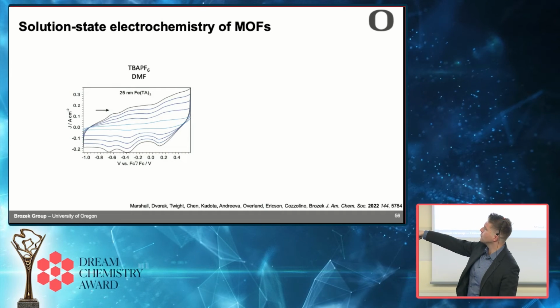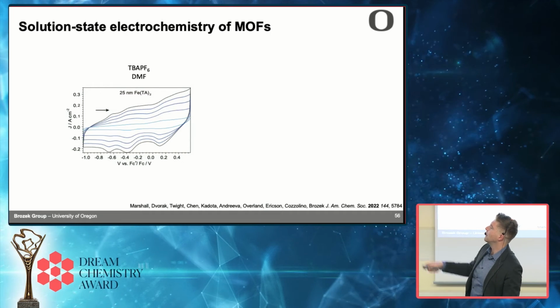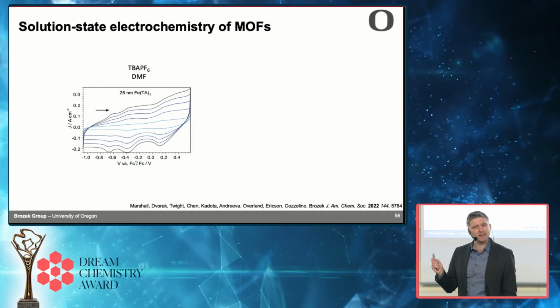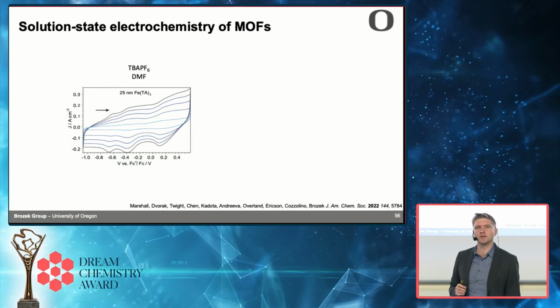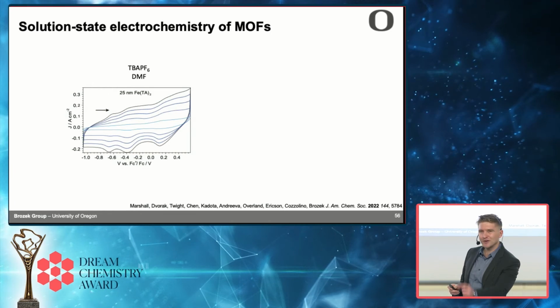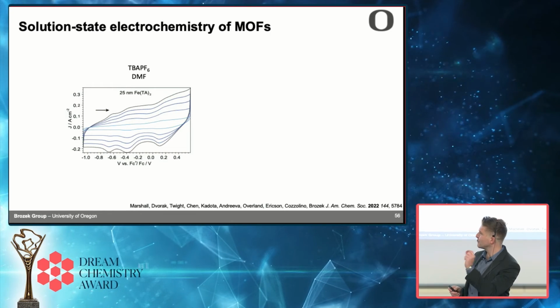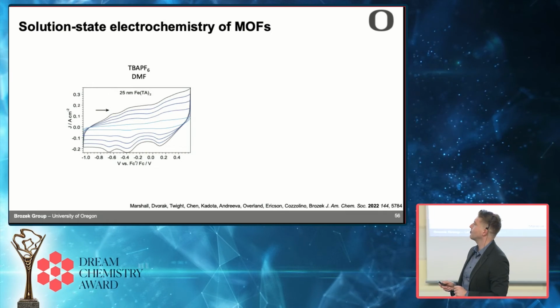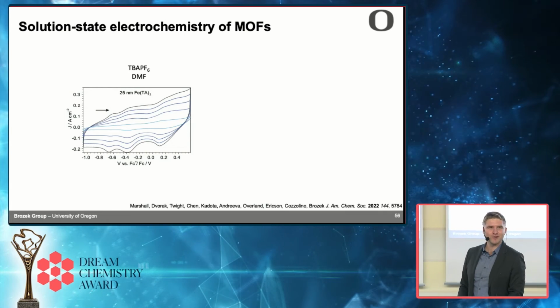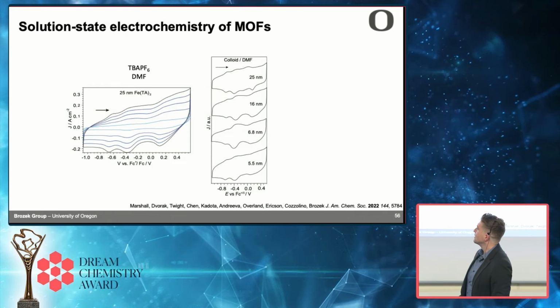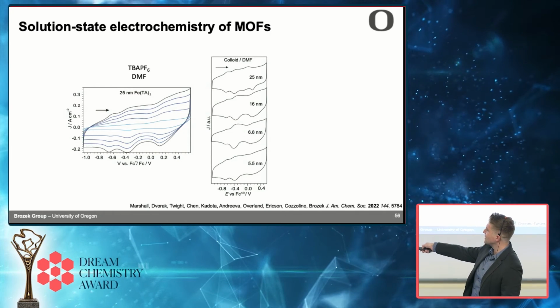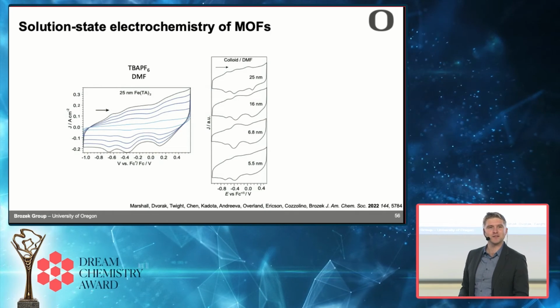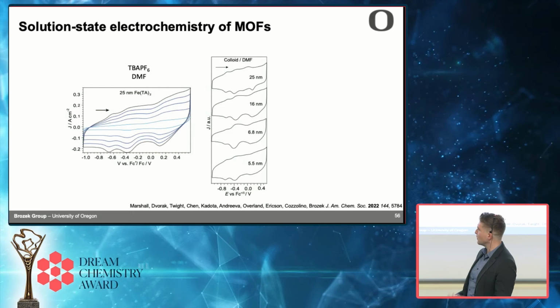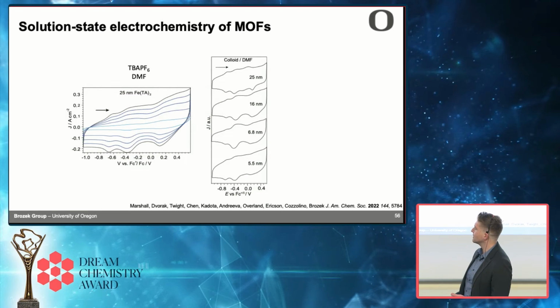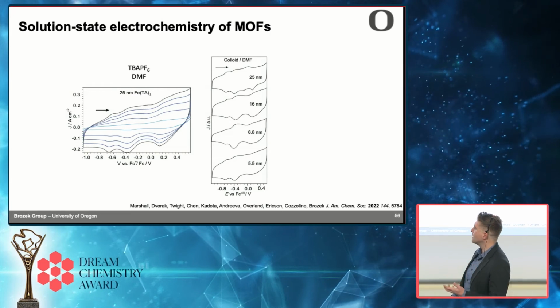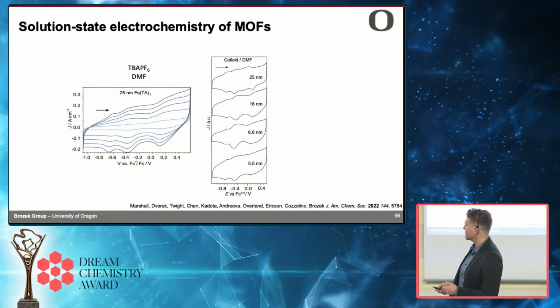You see multiple quasi-reversible waves. That was weird. That was unexpected because really there should be just one type of iron environment in this material. I mean, crystallographically there are two, but really they're so similar we should have just seen one. So we thought maybe this is just an impurity. Okay, so let's repeat this again. You could repeat this for all the different sizes that we can make, and we see qualitatively similar traces, multiple quasi-reversible waves.